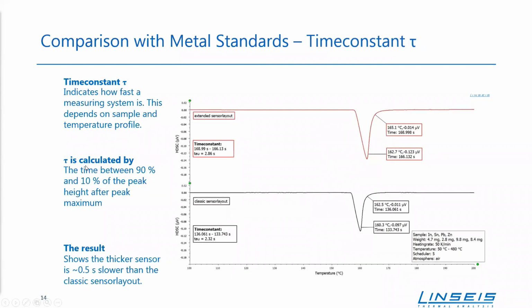But now, yeah, where the pros are, there are also some cons. And in this case, it's the time constant tau. So what we do here for this evaluation is we take the level at 90% and 10% of the falling ramp, so after the peak maximum of our melting peak, and then we do our evaluation. And as you can see here in the screen, the tau of our extended sensor layout is 2.86 seconds for this sample and this heating rate. And for the classic sensor layout, it's 2.32 seconds. So the classic sensor layout is around about 20% better than the new prototype.